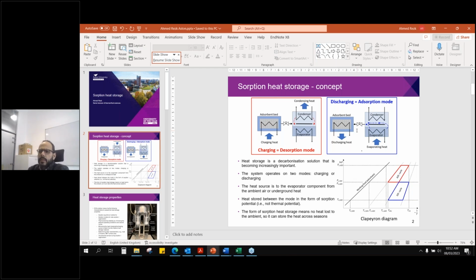The main challenge, which you might or might not know, is that we have a lot of materials that work well with water, for example, if we're going to use water as a working fluid. But the problem is these materials are thermally very poor conductors, and the rate of heat transfer is very slow. It is like insulation, like silica gel and zeolite. You can heat them, but the rate of heating and cooling is very slow. So if you have a surplus amount of heat and you need to capture or release it very quickly, depending on the demand, this would be the main challenge. That's why I develop new material.